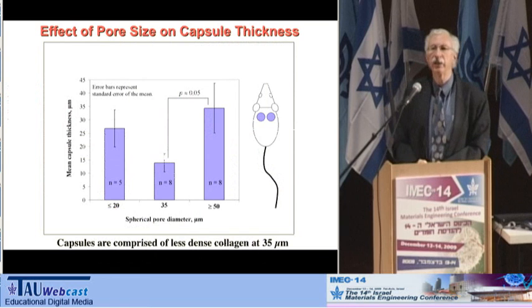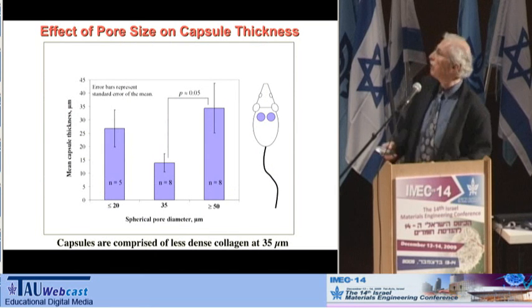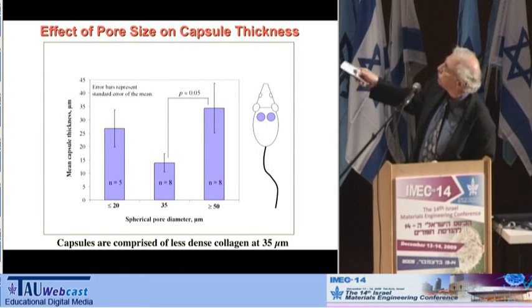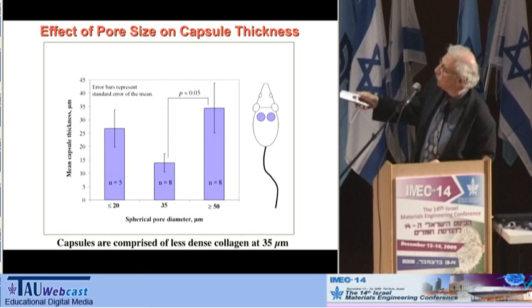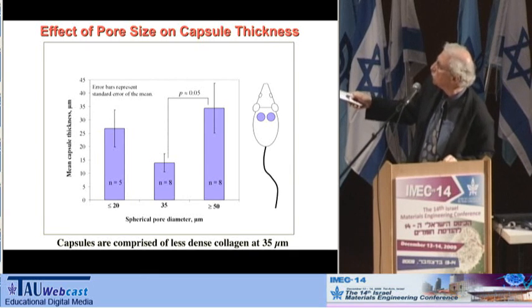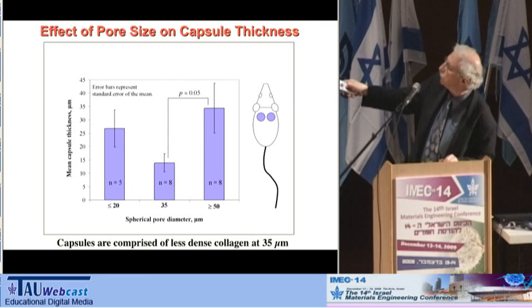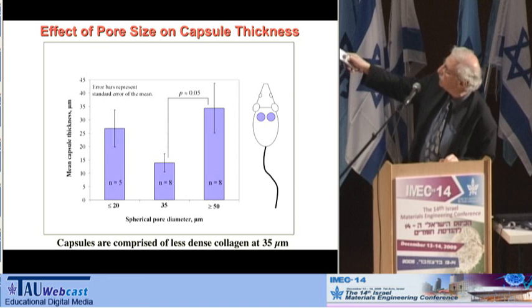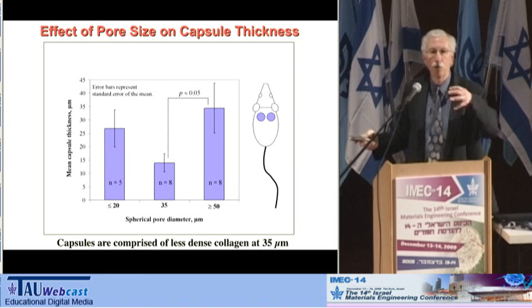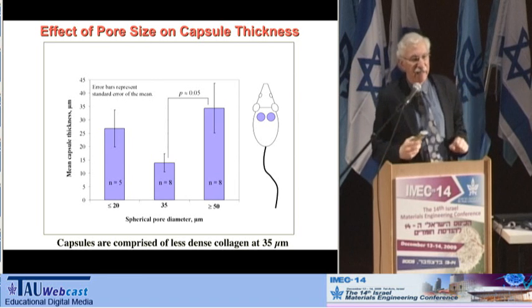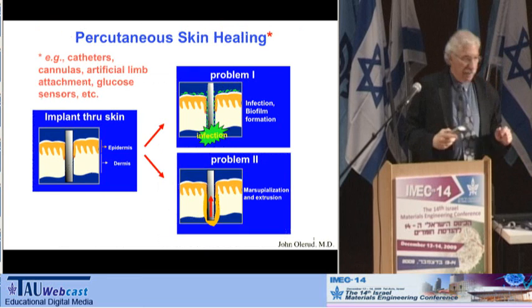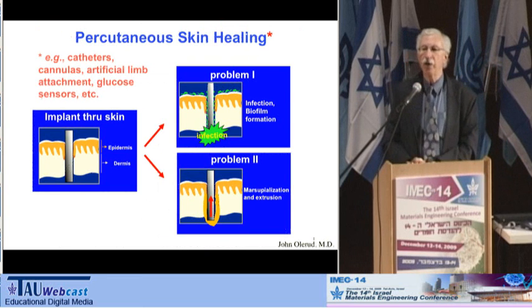If we look at this collagen capsule, the foreign body capsule, we find there's a minimum at 35 microns in the healing. And interestingly, although I don't have the data here, we do have the data that we sometimes present, the capsules are comprised of less dense collagen. So as well as the capsule being thinner, this is actually a rather open, diffuse collagen rather than a dense bag.